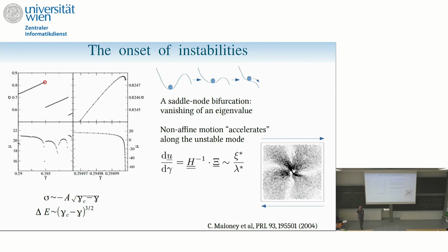If you want to predict the occurrence of instabilities, you need to use a higher order derivative of the potential energy surface. You need to go up to third order at least. If you can calculate your potential energy at higher order and use this relation, you can essentially back out this relation to try to guess the instability. Strikingly, at the beginning of every elastic branch, you can guess where it ends, just by looking at the high order derivatives of the potential energy surface.